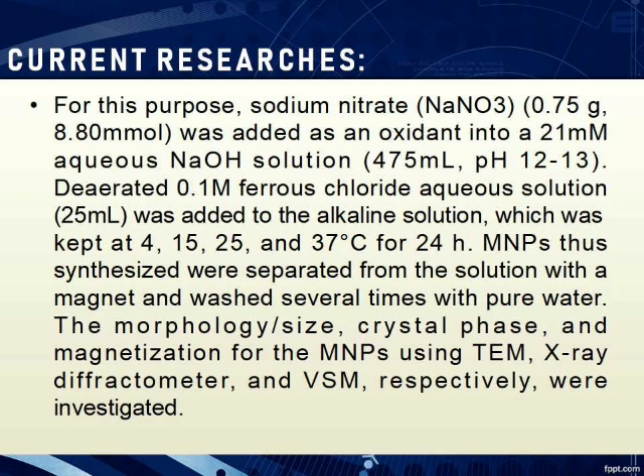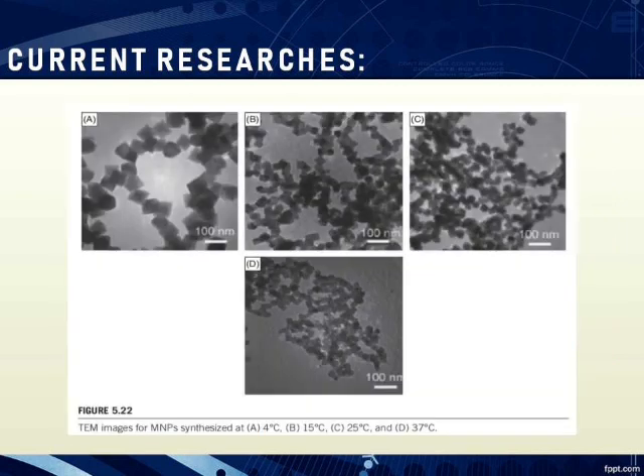As you can see in the picture, it shows that increasing the synthesis temperature from 4 degrees Celsius to 37 degrees Celsius leads to a decrease in the MNP's size and changes the MNP's shape. Furthermore, the size distribution of the synthesized MNPs becomes wide. The size distribution increases from 5.5% to 15.5%. This indicates that a higher reaction temperature accelerates both nucleation and growth of the magnetite crystals in the aqueous solution.